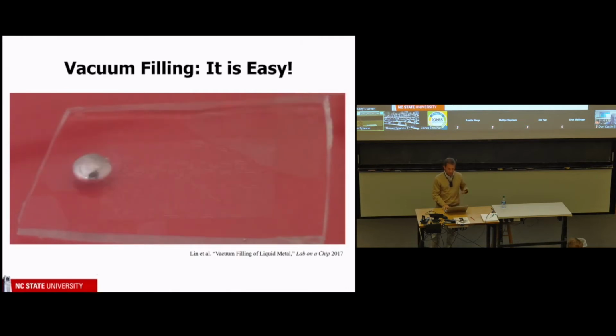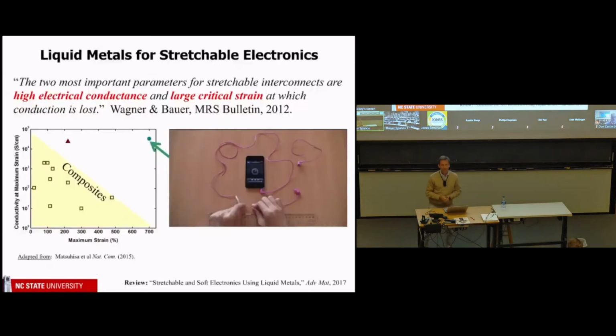All right, so at the end of the day, if you can get this into, say, a piece of rubber, you can make wires that are stretchy like a rubber band. And this breaks a traditional trade-off that you find with composites. With composites, you take something rubbery that can be stretched to a high value but not conductive at all, and you can make it more conductive by adding things like silver or carbon, but at the expense of making it less stretchable. We're able to get something as stretchy as rubber and as conductive as a metal.